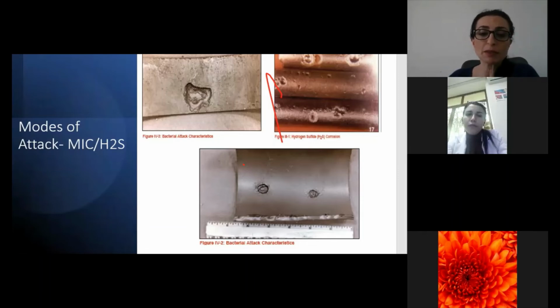Corrosion associated with bacteria is usually pit corrosion. You see some examples in this slide. So what types of bacteria cause pit corrosion? These are sulfate-reducing bacteria, iron oxidizing bacteria, acid producing bacteria, sulfur oxidizing bacteria, manganese oxidizing bacteria, and slime forming bacteria. As you see from these photos, it's an example of the morphology of MIC. Sometimes when we want to define corrosion problems, we look at the metal surface. This is just the appearance of the metal, just observation. By morphology, I'm not saying that it defines the corrosion type, but we can tell what type of corrosion appears here, but it's not proved each time.